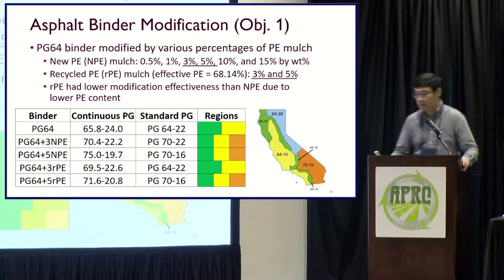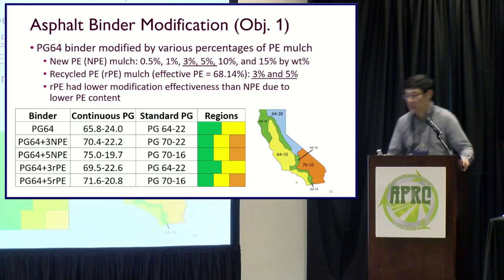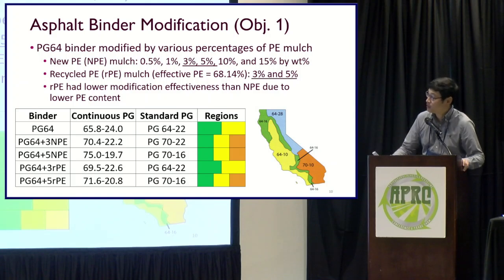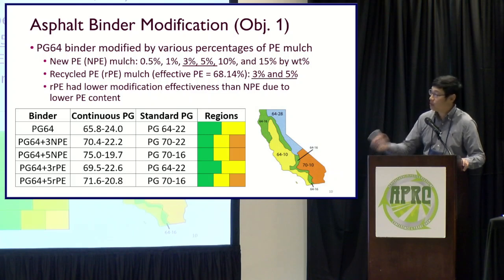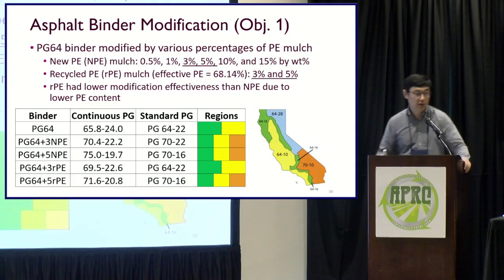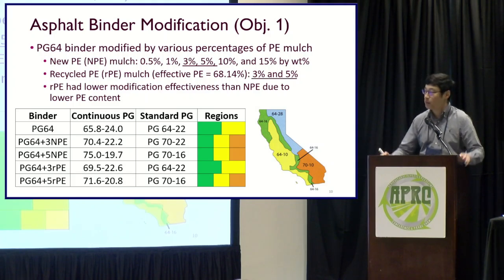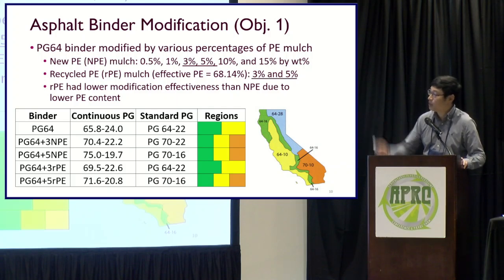And then we come to the polymer or the plastic modified asphalt binder. So we start with the PG 64 binder modified by different percentages of the PE mulch. We use a new PE mulch as a control one. So we start with low percentage, 0.5%, 1%, 3%, 5%, all the way to 15%, and we figure out 3% and 5% are the appropriate amount of the plastic to modify the asphalt. And then we come to the recycled PE mulch. So we have the effective PE content, which is around 70%, again at 3% and 5%.